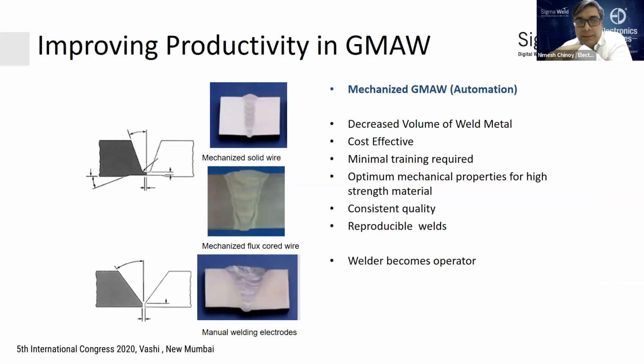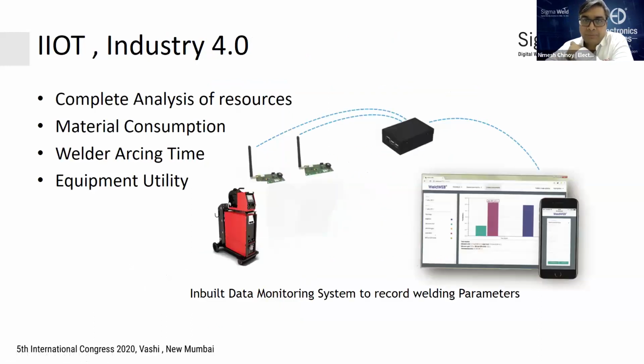If you look at this mechanized GMAW process, this is for a manual one, many passes, not very clean. You have to clean after each pass. If you go for mechanized flux cored wire, a narrower groove, lesser material to be deposited, and fully mechanized, you can see the number of passes is reduced drastically. Less number of passes, more weld deposit, and lesser cost overall.